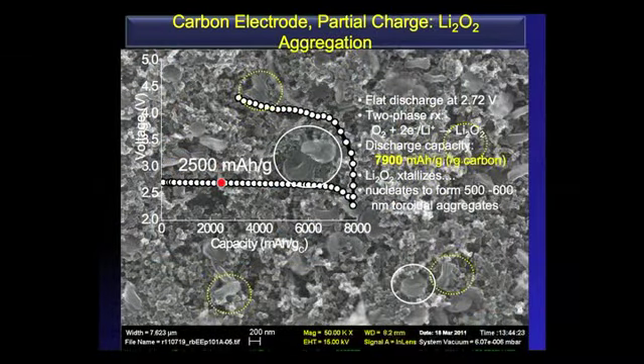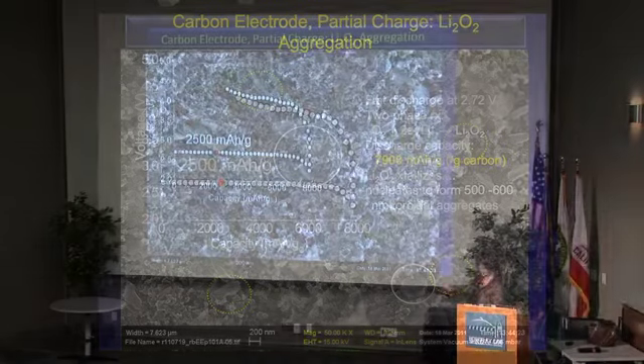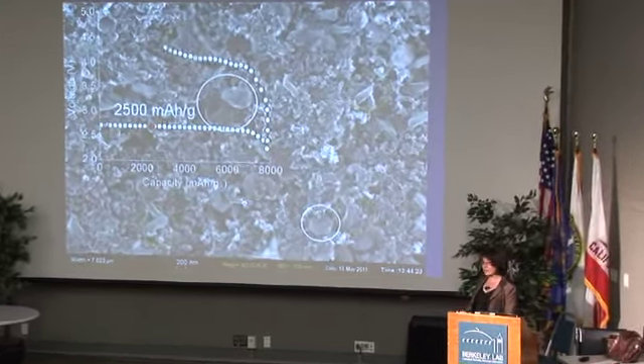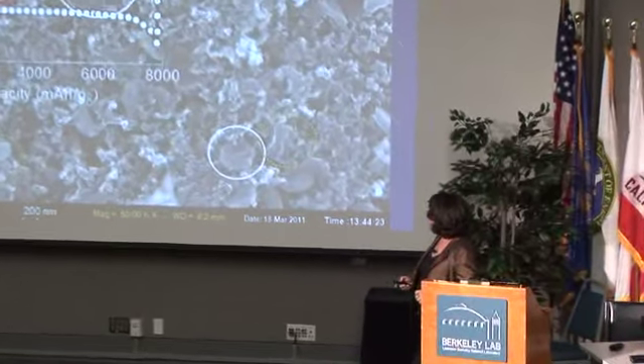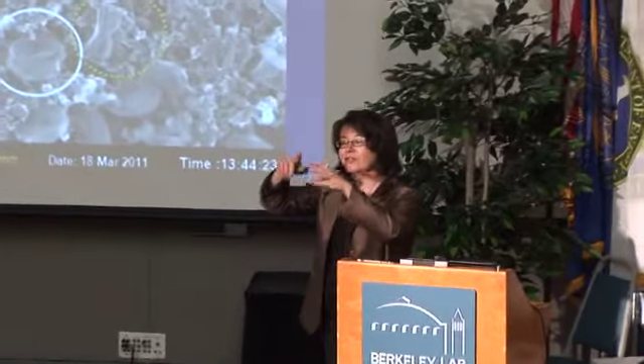And you can also see that the peroxide has nucleated to form these interesting little toroidal aggregates. So this is at 2,500 milliamp hours per gram along the curve, and it's a little hard to see here, but those are shown here. These are sort of pre-toroids shown by these little yellow dotted lines, and you can also see real toroids that are starting to form with these white circles. And this is characteristic of peroxide formation. And the important thing here is that it's not filling the pore space the way we think. It's actually growing right out of the surface of the carbon.